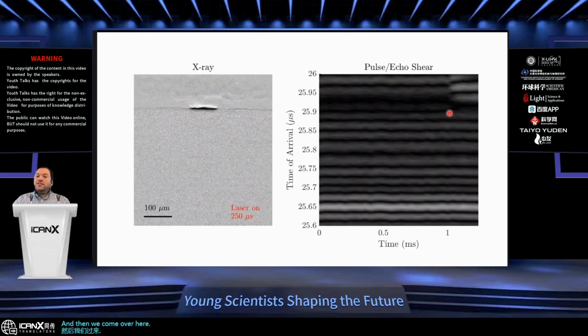And then we come over here. This is the analogous result as I presented earlier with the thunder and lightning analogy. So we have arrival time of the ultrasound. We have experimental time, and so this is milliseconds. And so the laser turned on at this point, and the current time amplitude response is this far edge here, okay? And so the signal that we see at this point exactly corresponds with the scattering of the melt pool over here. Okay? And so the video that I'm going to show shows the dynamics of this.